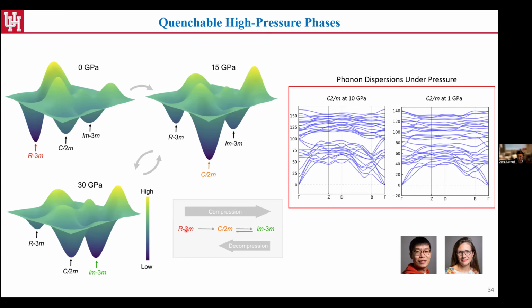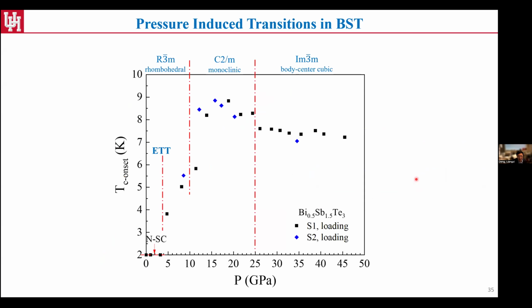At 1 GPa, there's no imaginary frequency appearing here, so that supports the idea that this phase can really go back to much lower pressure, although it originally needs at least 10 GPa to form. So that's very nice. After identifying all of this, we put out these 3 structures. So allow me to ask you, if you are going to do the quench, which range are you going to choose?